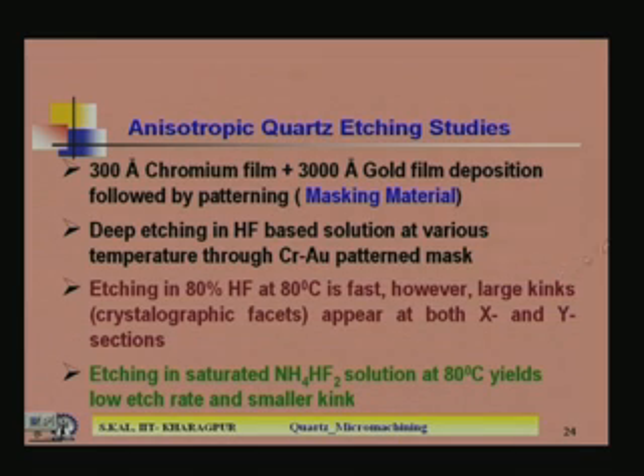Now, one of the problems we face if we use only hydrofluoric acid is that it gives you some kind of crystallographic facets or kinks at the surface, and if a lot of facets and kinks are produced, then the regular structure of the quartz crystal will not be produced. In that case, if you use it as a vibrator or resonator, its frequency of oscillation or resonance frequency will change, because the resonance frequency of that crystal microstructure depends on its shape.